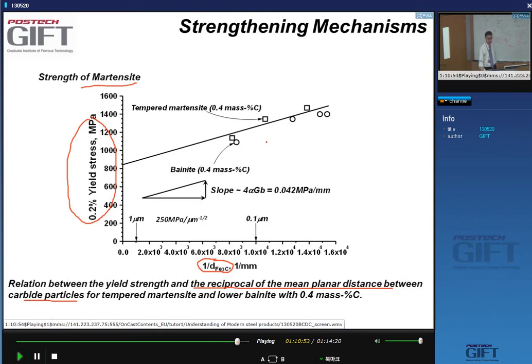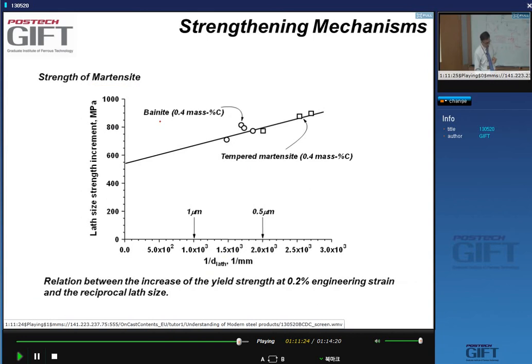And at that moment, yes, the martensite looks very much like bainite, because bainite is really structurally very similar to martensite in terms of dislocation density, in terms of carbide densities, in terms of size of the structural units. Okay, so here you can see bainite and martensite data.